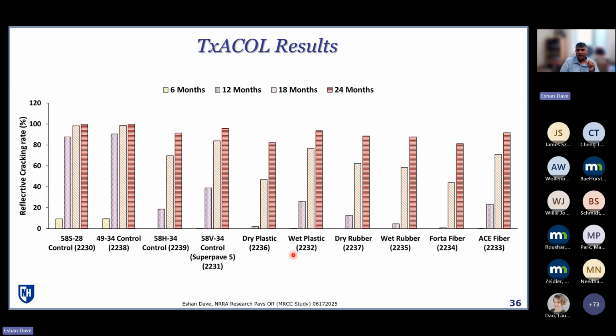If we look at the results from that tool, now we can start to see a little bit more alignment with what our lab test told us. So you have your control. What we are looking at is what percent of your underlying joints or cracks have reflected through. 100% would mean every joint has already gone through. You can see control had a very high amount of cracking already by the time you went to 12 months. We already had about 90% of those joints reflected through,